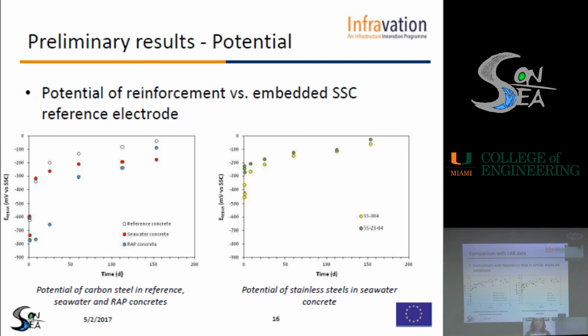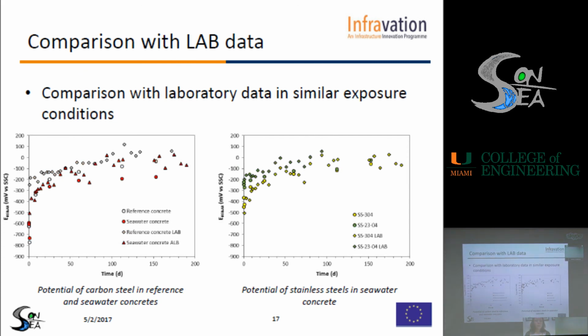What we did so far was to compare these results with the ones that we obtained from the laboratory specimens in similar exposure conditions, and we can see that there was a good agreement between the two. Of course, it is quite difficult to interpret these results. They need to be monitored for longer periods of time.